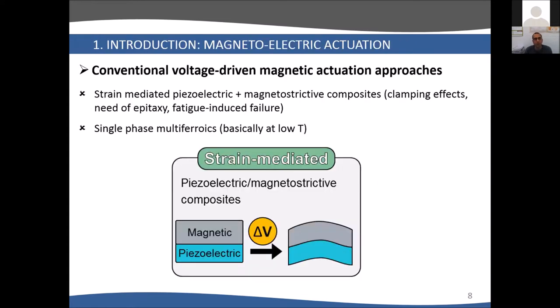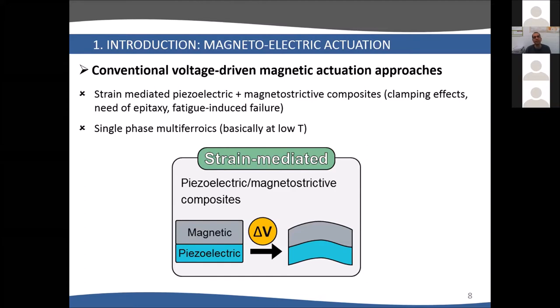To what extent is it possible to control magnetism with voltage? The conventional way could be using strain-mediated piezoelectric magnetostrictive composites, as in the picture here below, where you apply a voltage, the piezoelectric deforms, this deformation is transferred to the magnetostrictive component. Because of the Villari effect, you can change the easy axis of this magnetic layer. However, if you do this on a rigid substrate, you have the problem of clamping, so the piezoelectric will not be able to deform. And after some usage, you have fatigue effects, which would not be very good for spintronics.